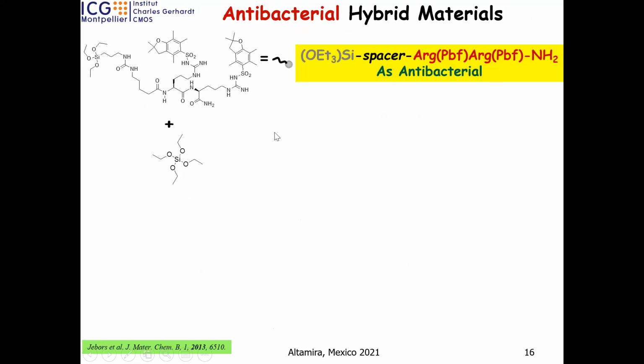So first example here, what we prepared. We prepared this antibacterial peptide with a spacer. The spacer is a classical one here. This peptide was mixed with tetra-alkoxysilane. You know, it's a famous precursor for silica. And you can control the ratio. In general, it's 5% and 95%. Why? Because silica, SiO2 at the end, is too small, while your peptide is very, very big. This part doesn't change. It's only this part that moves a little bit.